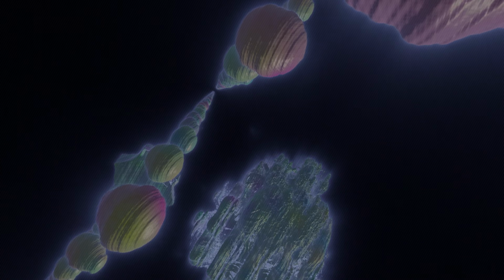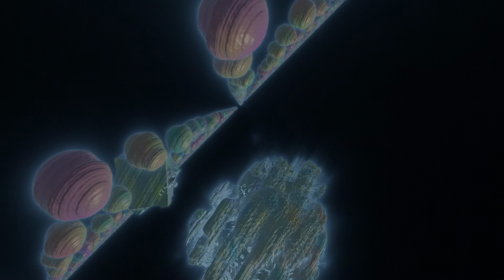And the big advantage? Sample size. IXS can be performed on extremely small samples, micrograms of powder, or single crystals just tens of micrometers across. This is a huge deal for studying novel materials synthesized only in tiny quantities. Plus, X-rays don't interact strongly with electron spins, so IXS is great for studying phonons in magnetic materials without getting confused by magnetic excitations, magnons, which can be an issue for neutrons.